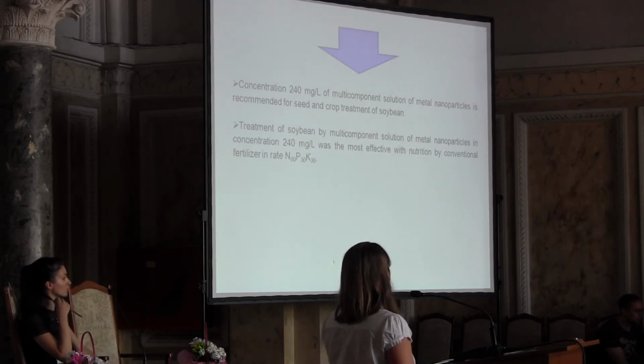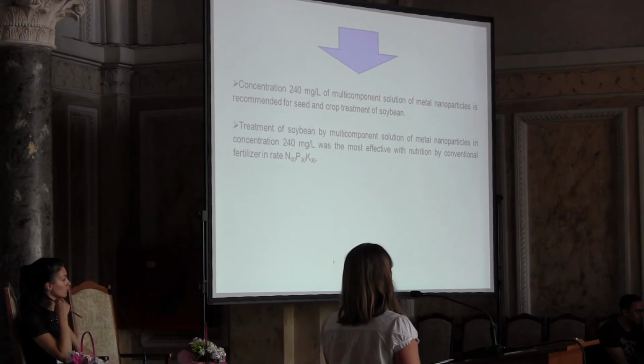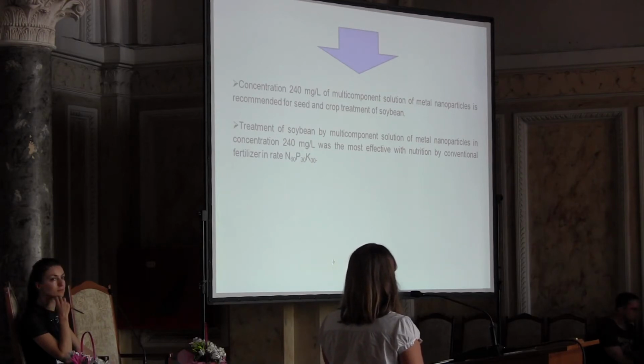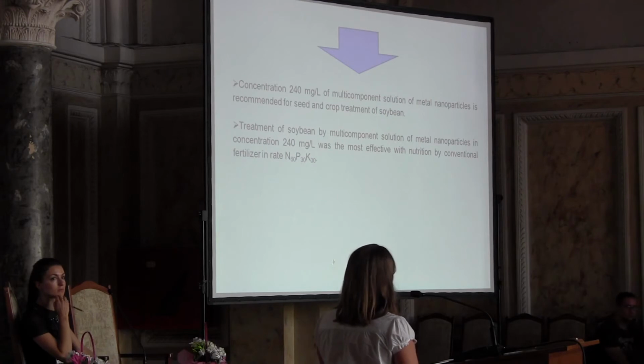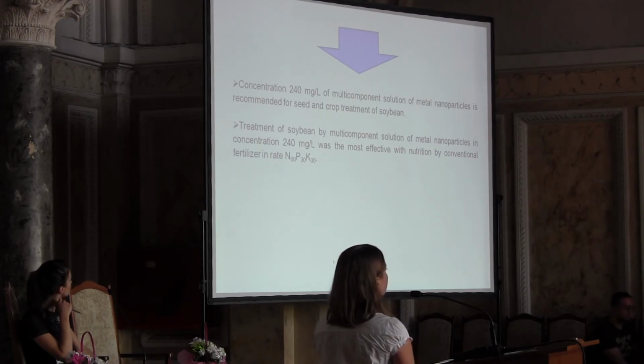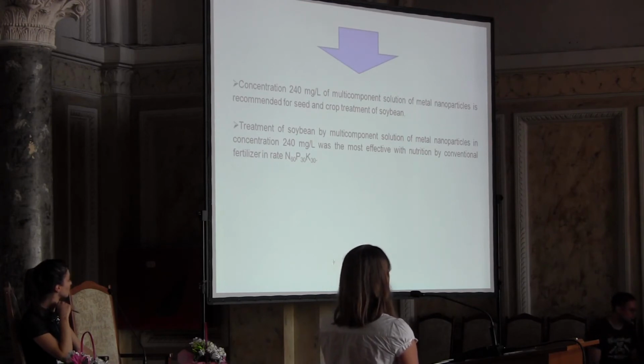So a concentration of 240 milligrams per liter of multi-component solution is recommended for seed and crop treatment of soybean for common cultivation of soybean, and treatment of soybean by multi-component solution of metal nanoparticles in concentration 240 milligrams per liter was the most effective with nutrition by traditional fertilizers at the rate of nitrogen 60 kilograms per hectare.